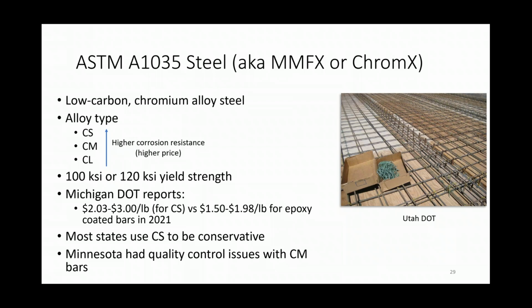But actually, most agencies that participated in the scan reported that they choose not to rely on that high strength, so they just use it as a one-to-one replacement of our good old grade 60 steel, or just cap the yield strength in the design to be conservative. And there isn't all that much data available for the long-term performance of these bars.